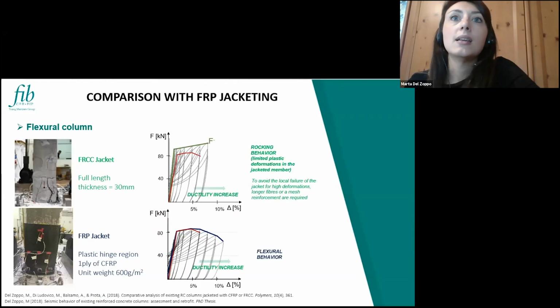And if we look at the comparison of the behavior, we will see a big difference between the two performance curves. So basically, when we deal with fiber reinforced polymers, of course, we don't have any increase in lateral stiffness or any increase in flexural capacity, because we are just applying a passive confinement for the member. But we are preventing any kind of sudden failure modes that can reduce the ductility of the specimen, and we allow a very slow softening branch.